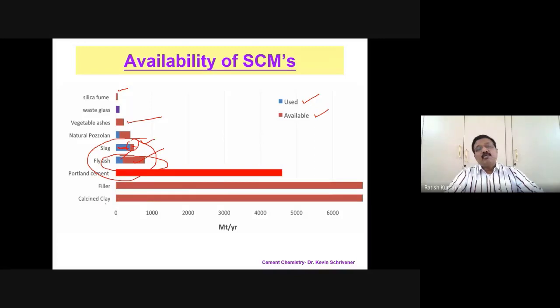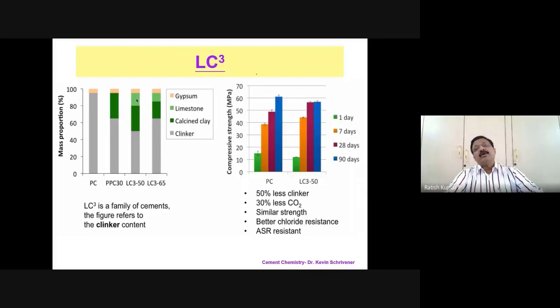Now, what is available in good number as compared to the Portland cement here is the filler, which is nothing but calcium carbonate, and then also this particular thing, which is calcined clay. So that is the reason why there is a lot of research going in the area of limestone calcined clay cements, which you can notice. For example, if I try to typically compare the Portland cement with respect to the limestone calcined clay of 50% or 65%, you can see a good amount of strength gain has occurred as compared to the Portland cement.